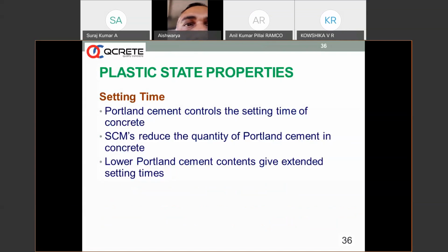Portland cement controls the setting time of concrete, and SCM reduce the quantity of Portland cement in concrete. Lower Portland cement contents give extended setting times. So many times it helps a ready mix company to transport the concrete, because if you take a control concrete, that is concrete without SCM, with a setting time of about 4.5 to 5 hours, the setting time with fly ash or GGBS is extended by say 1.5 to 2 hours. So that gives a little flexibility for a ready mix company to transport to longer distances.